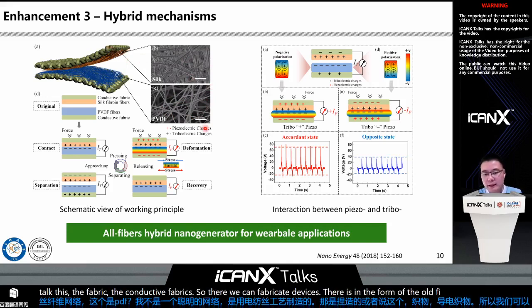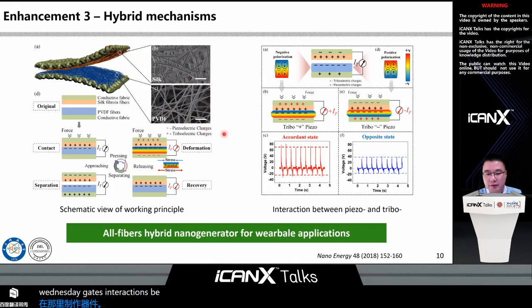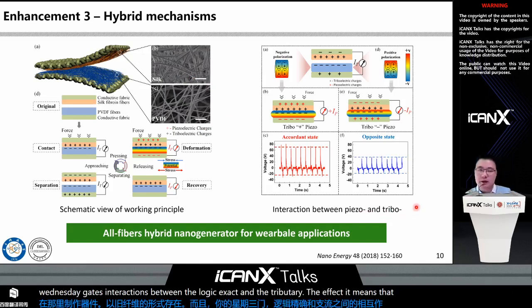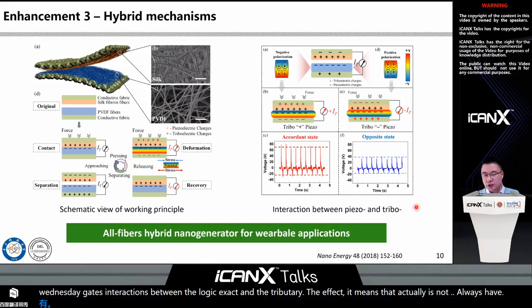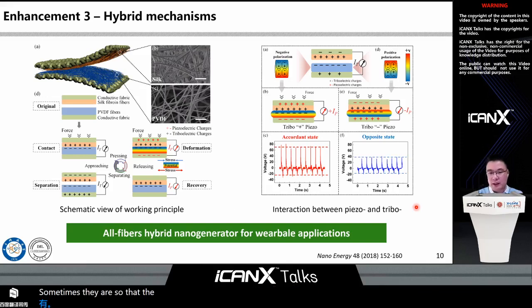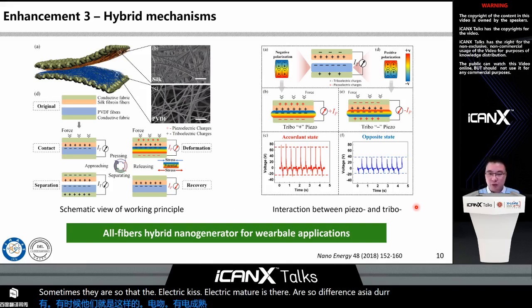We also investigated the interaction between the piezoelectric effect and the triboelectric effect. It means that they don't always have a positive interaction. Sometimes they also have negative interactions. For example, we know that piezoelectric materials have different polarization directions. If you change these directions, maybe the generated charges will not stay in the same direction as those of the triboelectric generator.